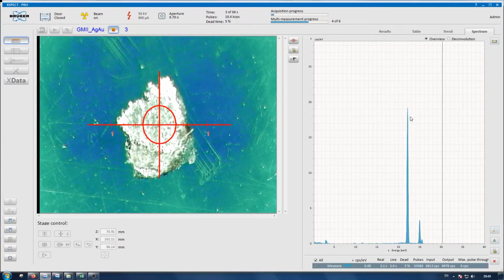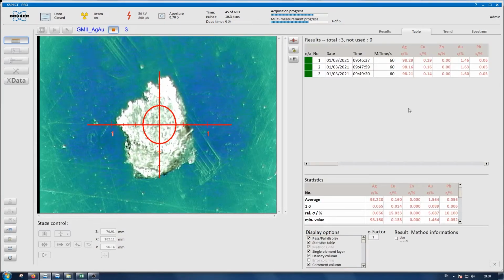Note that this method of exposure to the sample is completely non-destructive. The next step is for the device to measure the obtained spectra. Already at the stage of processing, it is clear that among all the elements in the spectral diagram, the element argentum, i.e. silver, marked in blue on the diagram, stands out significantly. Much less represented elements are copper and gold. The spectrometer also detected lead as a part of the sample point. As a result, the test revealed that the composition of the metal at this spot of the rhyton fragment is an alloy of 4 elements, with a significant predominance of silver.